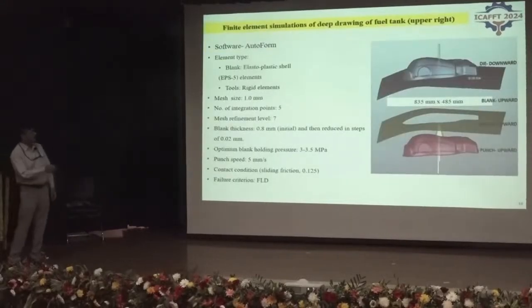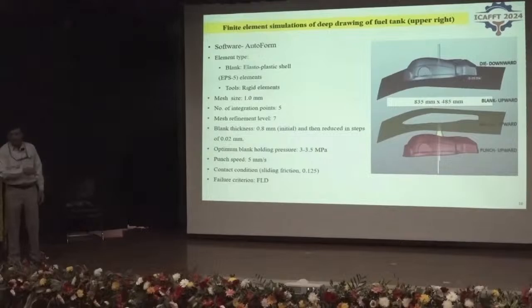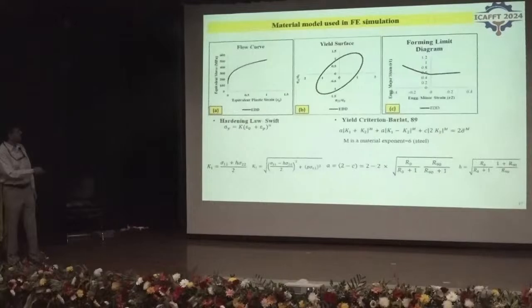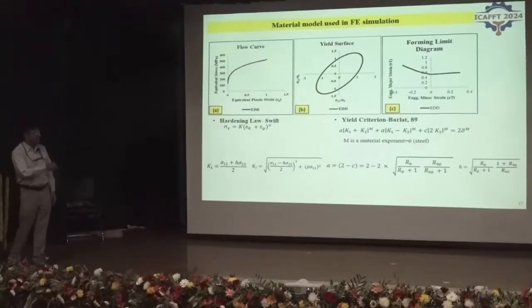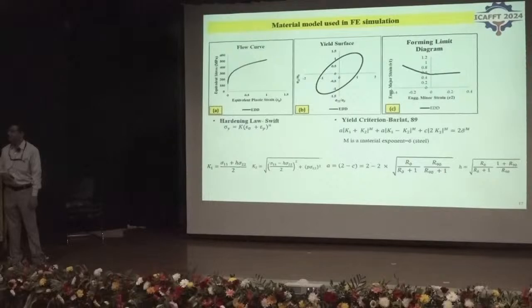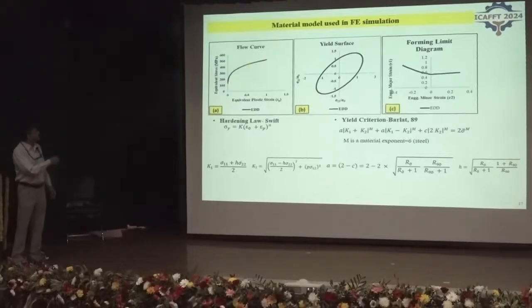And this is the finite element model which we have created for simulation of the fuel tank, and I don't want to go into each and every detail. And this is the material model that is required to define the hardening behavior and the yield behavior of the material in any software that we generally use. So we have used Autoform software, and this is the hardening curve as per the Swift hardening model, and this is the yield surface of the material, plotted using Barlat 89 criterion, and this is the forming limit curve of the material which is experimentally determined.